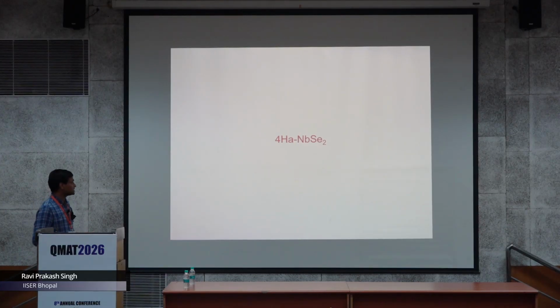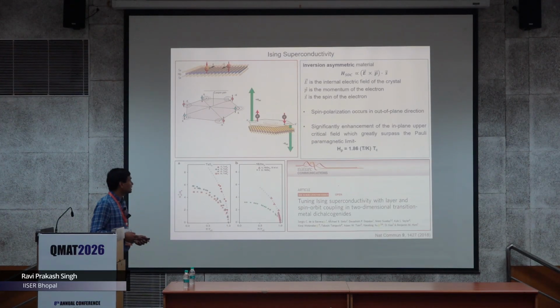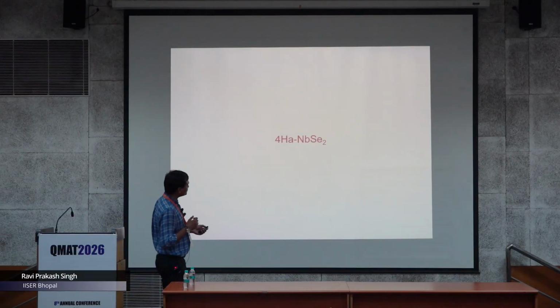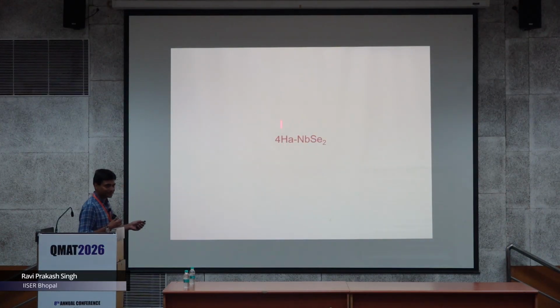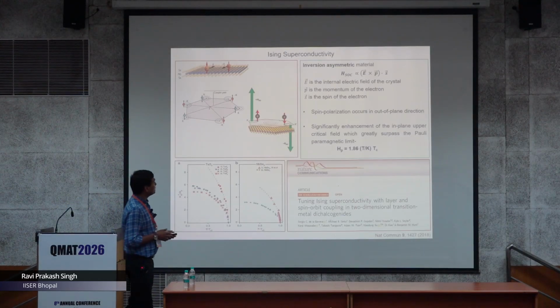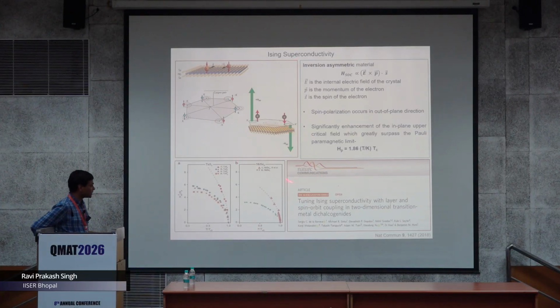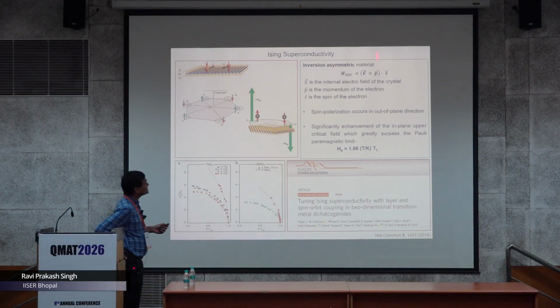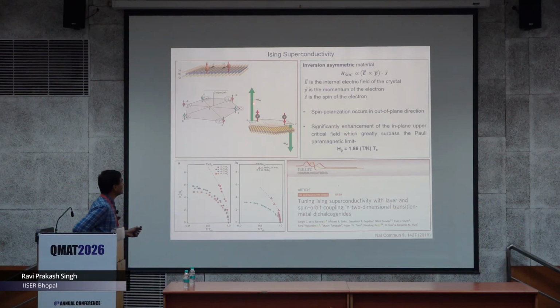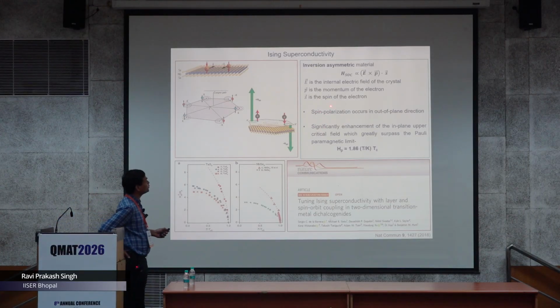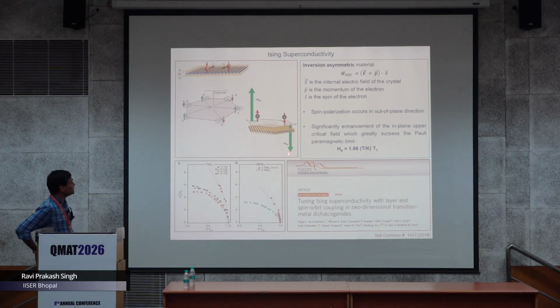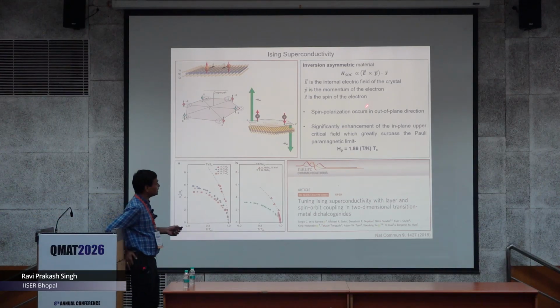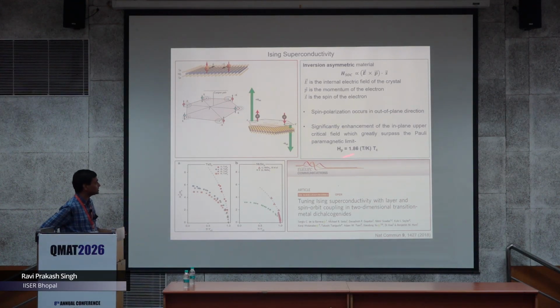So first I will talk about 4H NbSe2. This is also a non-centrosymmetric superconductor. It is hexagonal, but different compared to the 2H structure, because we want to realize Ising superconductivity in this one. Ising superconductivity is like, if you have an inversion asymmetric material, then at valley points you can get spin polarization out of plane, and this can give you a very high upper critical field, and it will basically surpass the Pauli paramagnetic limit by 5-6 times.